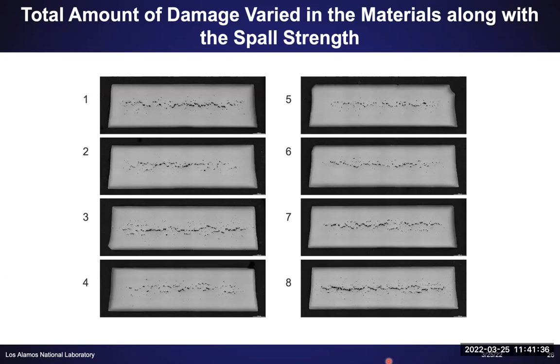But one thing as material scientists we're interested in is then trying to understand why that is the case. And when I'm talking about velocity time data, we've done a lot of work that has shown that if you just look at that and you are not able to look at what went on in the sample, you're only getting half of the story. So one of the things that I mentioned we do is we recover the samples after the experiments. We can cut them open and actually look inside the samples to see what damage looked like in the material.